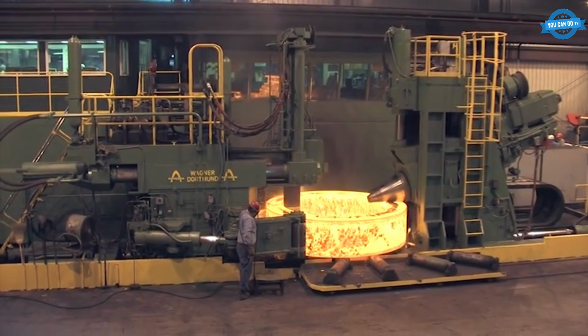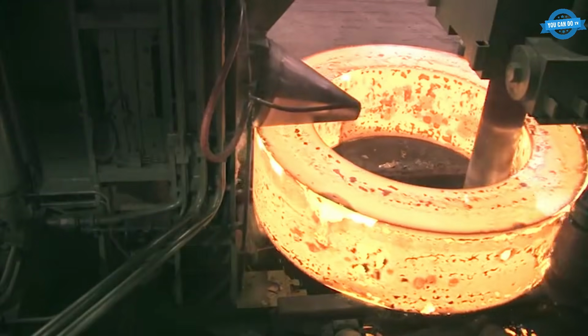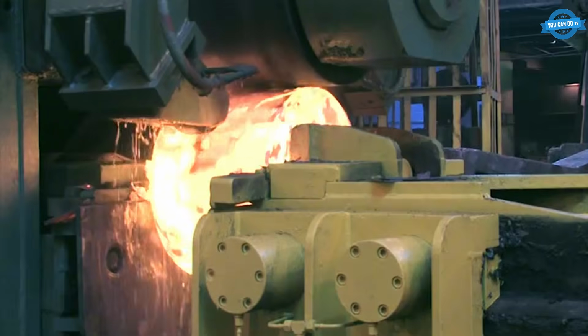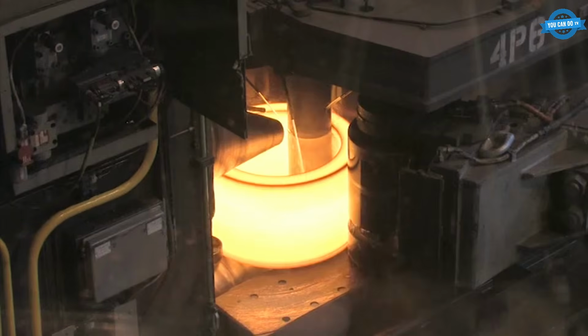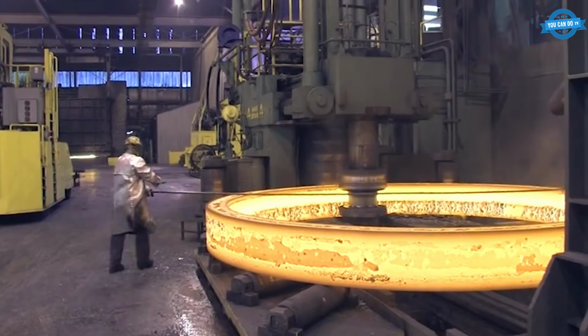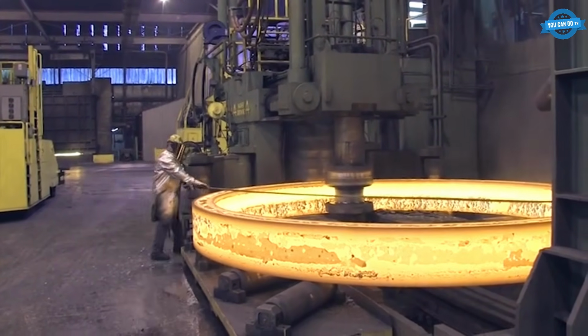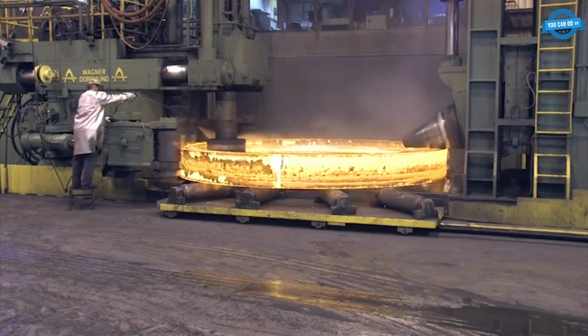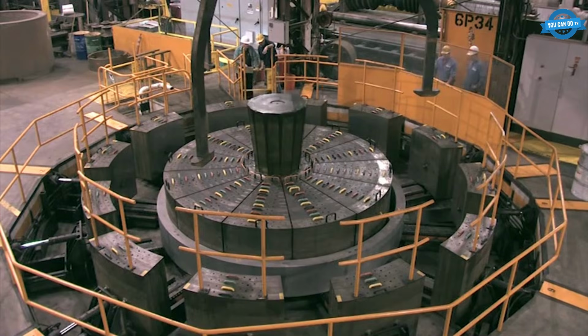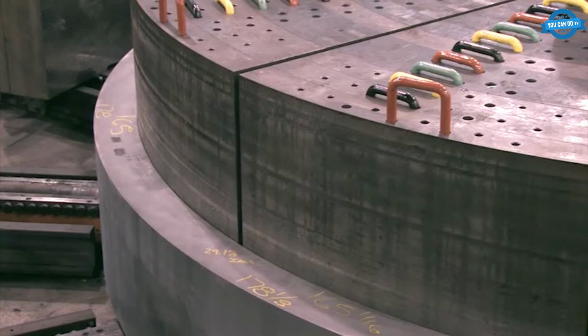Take a hot forged blank, pierce a hole through the center, and roll it outward. That's ring rolling. Rolled rings can reach over 240 inches in outer diameter and 60,000 pounds in weight. Grain flow runs along the circumference, which gives rolled rings toughness that a plate-cut ring will never match.